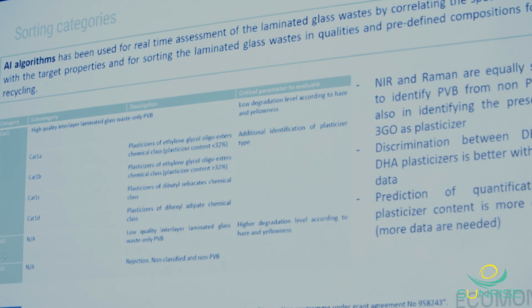Then we discriminate between category 1 and 2 depending on the quality, the degradation, according to the yellowness detected by the sensor and according to the haze. Here also the prediction is good because it's directly measuring the haze and the yellowness through transmittance values. And then within category 1, we have discriminated aspects related with composition, with type of plasticizer. Here we obtained better results with the Raman sensor, because in the case of NIR, there could be more errors between some types of plasticizers and between the minor plasticizers.